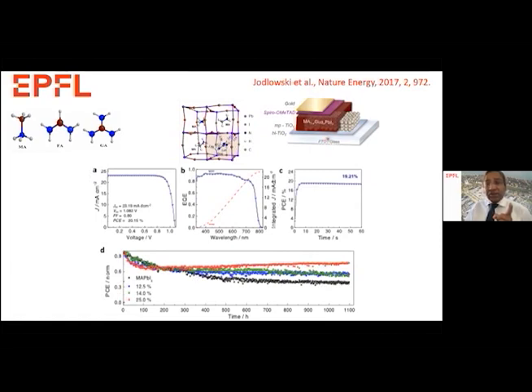Let's say it's still a mesoporous NIP configuration, as I discussed in the beginning. The power conversion efficiency is not very high, but it's in the range of 20%. The beauty of this guanidinium addition is enhanced stability up to 1,000 hours, with a small decrease in the initial burn-in stage, but it remains very stable up to 1,100 hours. So this is the composition engineering of cations.